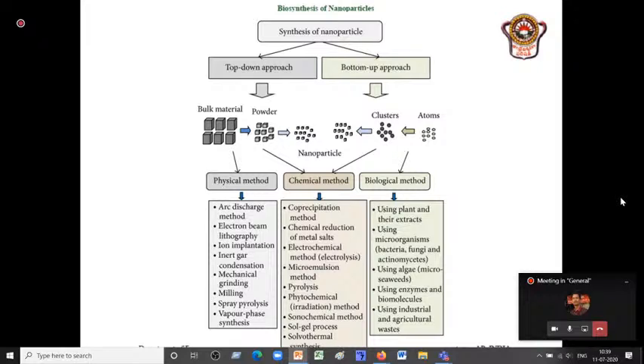They are almost all like basic chemistry. I don't think you require a highly sophisticated instrument. Now we have at least something like furnaces, high temperature furnaces we are using, but still many of these methods, like the co-precipitation method, are an ordinary chemical reaction. A chemical reduction of metal salt, simply use a reductant like sodium borohydride or any of the ordinary chemical reductants in the lab, so that immediately you will get it reduced from a metal ion to metal.